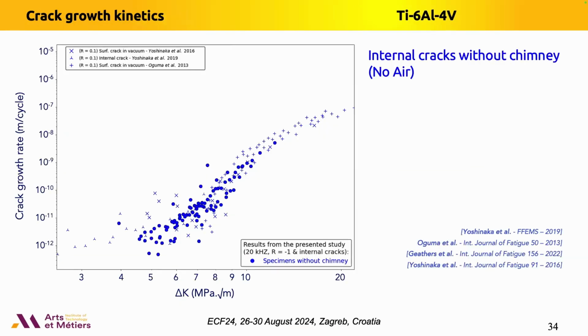So if you plot the kinetics of this crack in the Paris diagram, you obtain the following diagram. The blue round points correspond to our data without air in the crack. And these data are compared, this is the cross, with data coming from literature on a similar alloy at 20 kilohertz. So we can see that our data are in very good agreement with the literature data.